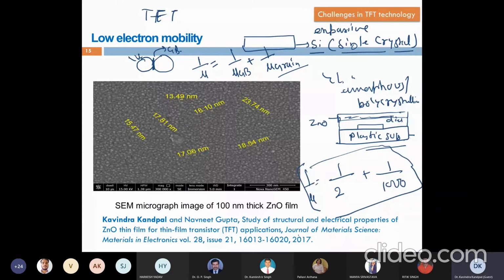The lower will dominate, right? Right or not? Am I audible? Yes, sir. So the lower will dominate, hence the effective mobility is cut down to 2 only. Though they have the grains, the grains are okay, but there is a guy which is walking very, very slowly. The carrier going through these grain boundaries is taking much time, and that is detrimental. That is what decides the mobility, not the grain. So you can clearly see the biggest challenge with TFT technology is the low electron mobility. It was not a challenge earlier, because earlier your demand was very less.